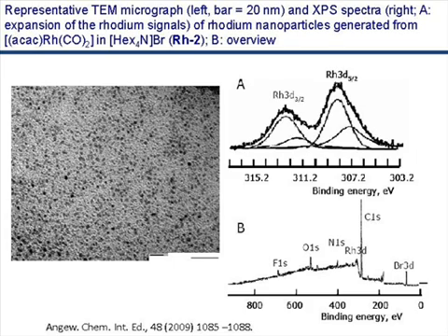What was the secret? Something was already proposed also by Baiker, who was also interested in CO2 pressure reactions. And what we found? During the reaction, CO2 with hydrogen on this catalyst is generating CO. CO is partially poisoning the rhodium, so it's not an invention. It's classic chemistry. CO is partially poisoning the rhodium, and rhodium in that case is not able to do the typical hydrogenation. So another case in this case was also nanoparticles.